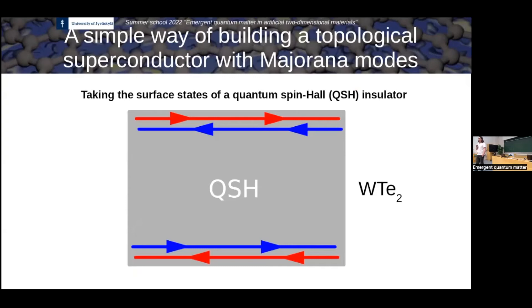So let's imagine that you want to engineer a one-dimensional superconductor that has a spin triplet order, and you want to do it with two-dimensional materials. A very simple way of doing this is the following. If you are thinking about a spinless superconductor, you can get spinless fermions in two different ways: you can apply an exchange field and lift one of the spin degrees of freedom, or you can just use helical states — states in which up electrons move in one direction and down electrons move in the opposite direction. These states are the states that appear in two-dimensional quantum spin Hall insulators, in particular two-dimensional topological insulators. As a reference, this state is realized, for example, in 1T'-WTe2 and many other transition metal dichalcogenide allotropes.